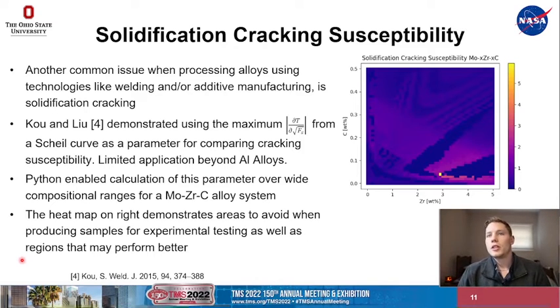Despite this, we use this model in order to run a wide compositional range for a molybdenum zirconium carbon alloy system. And that is what is shown in the heat map on the right side of the screen. This heat map is color indexed by the cracking susceptibility, with zirconium on the x-axis and carbon on the y-axis, with molybdenum as the filler element.